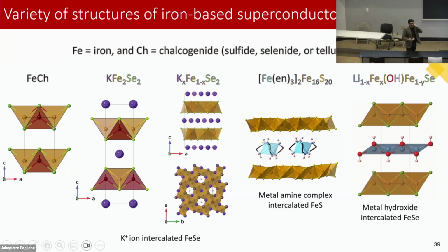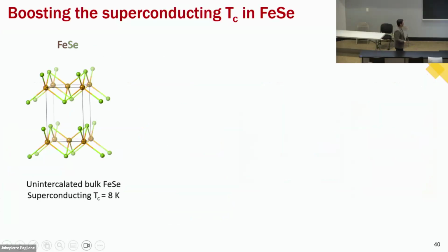And basically the limit here is about 43 Kelvin in the critical temperature in these, no matter what you're stuffing in there, whether it's potassium cations, lithium hydroxide. Sometimes you can put organic structures in there. These are very easy to work with if you're doing hydrothermal, solvothermal synthesis. And in fact, this is the only way you can make that superconductor, that lithium hydroxide one. It's only available through hydrothermal.